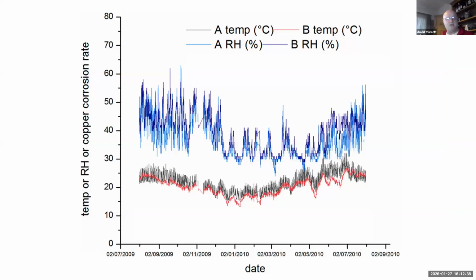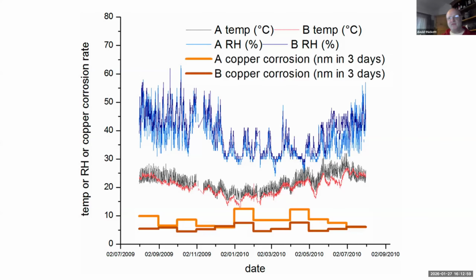If we look at the temperature and relative humidity data that we've often got, room B was generally higher relative humidity and lower temperature. From what you read about metal corrosion, you'd imagine that room B with the higher relative humidity would be more aggressive. We already had pollution data for those rooms. Feeding them into the damage functions showed us this was actually not correct. Room A is almost twice as aggressive, particularly over the period when the loan was proposed for.